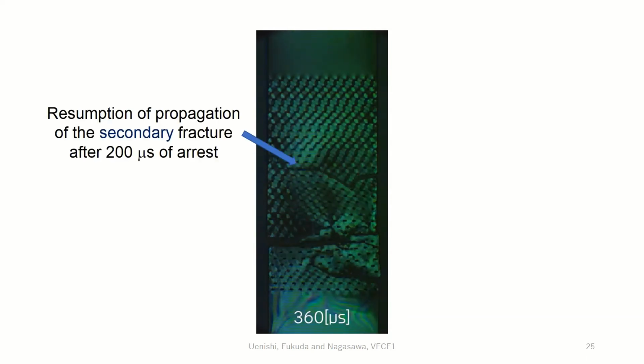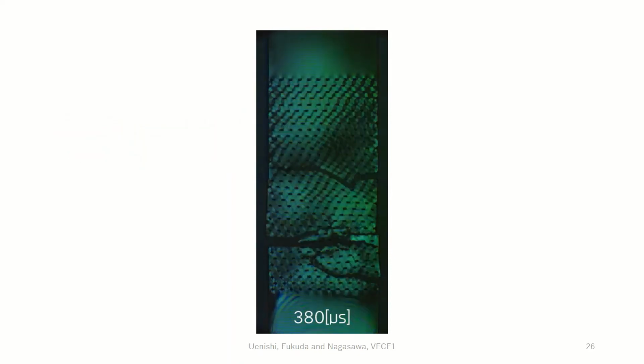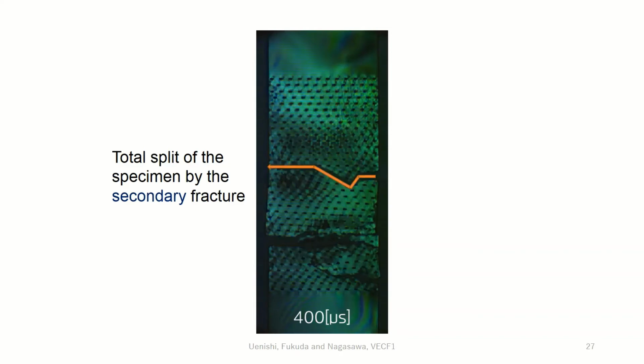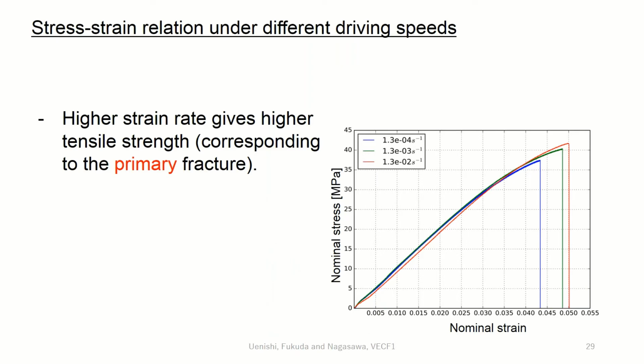Here and after, the resumption of the propagation of the secondary fracture can be recognized. At this point, let us summarize the experimental results. This diagram shows the relation between the nominal stress and the nominal strain experimentally obtained for 3 different driving strain rates. As predicted theoretically by Gomez, Uenishi, and Ionesco, a higher strain rate gives a higher tensile strength corresponding to the primary fracture.